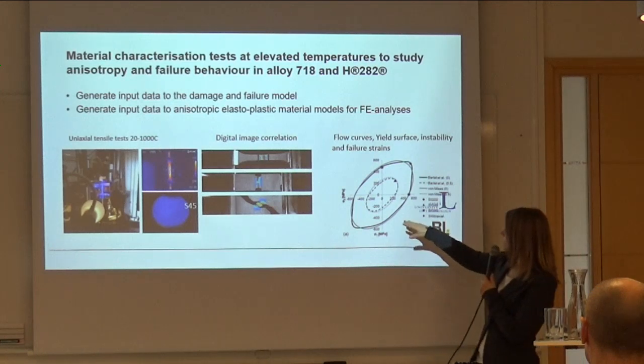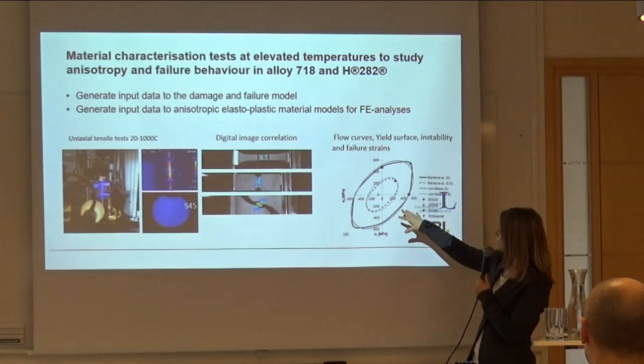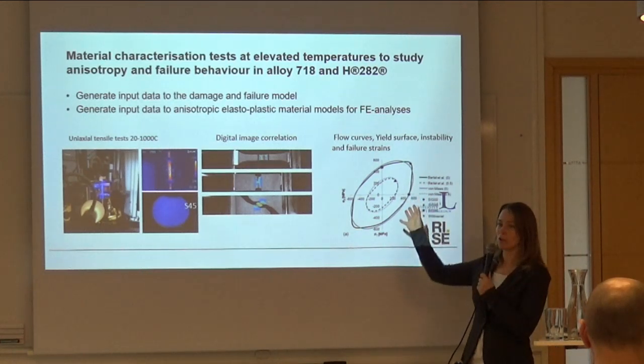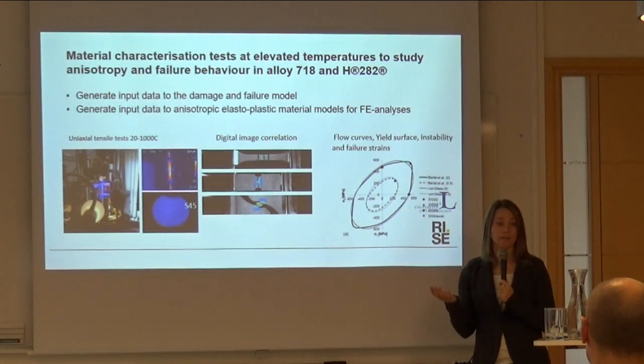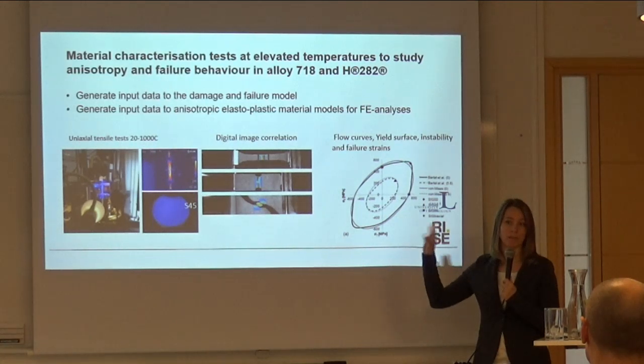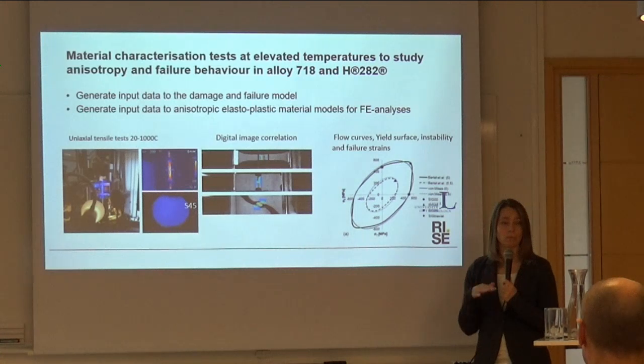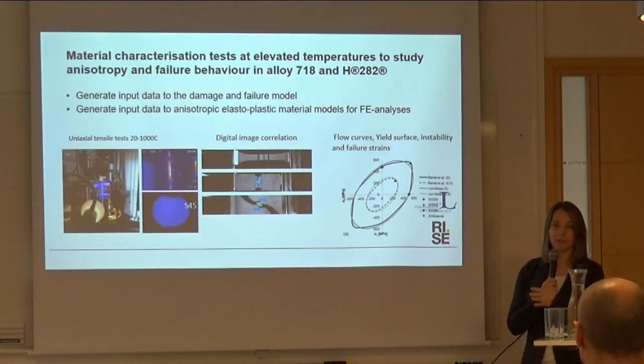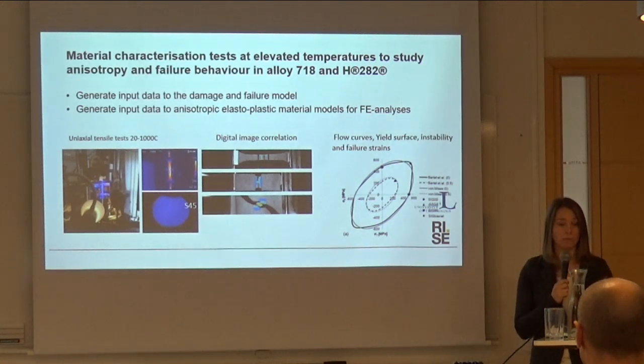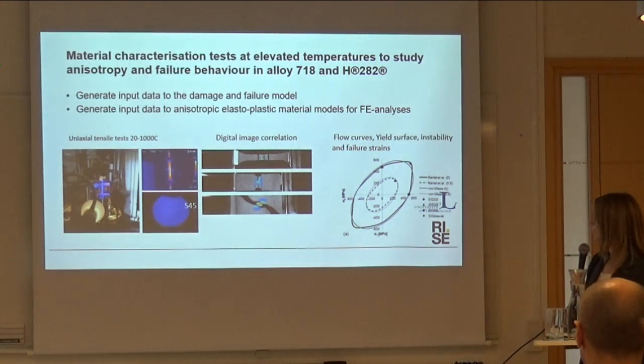So here is an example of a yield surface, which determines if the material is loaded elastically or plastically. We study a lot of anisotropic material properties, where the material has different properties in different directions. So we can feed the models with all the input at different temperatures, different strain rates and loading directions.